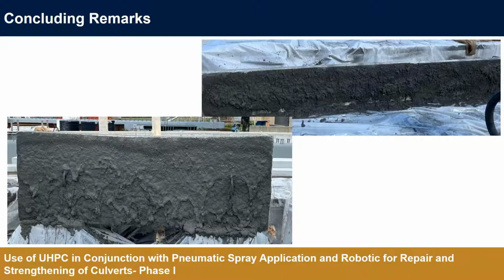Yes. Okay, so there are a lot of details, as we are trying to adjust the rheology of the material to make it buildable. But one technique was, after the first pass, we tend to move the nozzle back to the pump and circulate it, wait a few minutes for the material to dry out, and do another pass of shooting. So there is always a pause between the shooting passes.